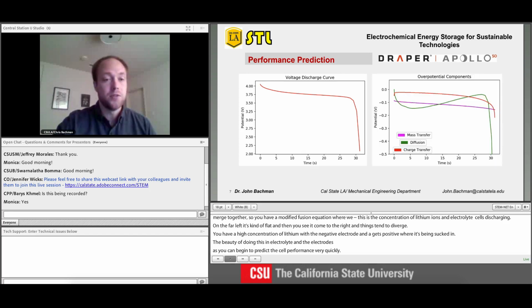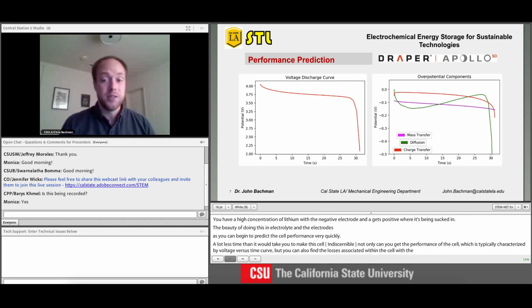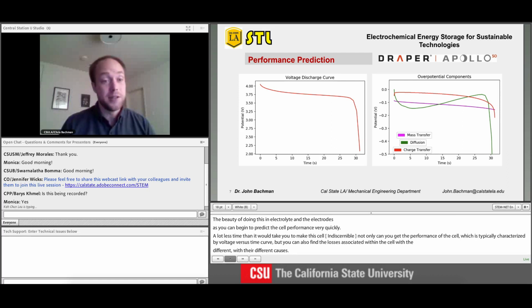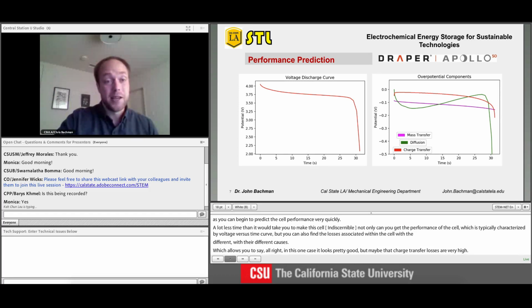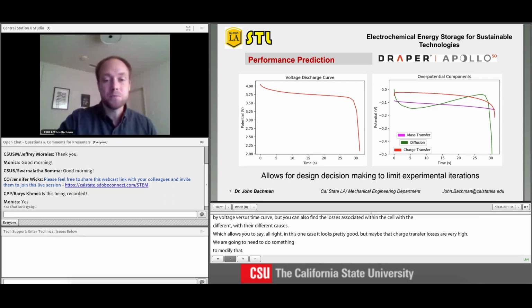And not only can you get the performance of the cell, which is typically characterized by a voltage versus time curve, but you can also find the losses in the cell with their different causes, which allows you to identify, all right, in this one case it looks pretty good, but maybe the charge transfer losses are very high, so we're going to need to do something to modify that. And so this really allows you to narrow down the landscape and allow them to build much fewer cells around an optimized performance.